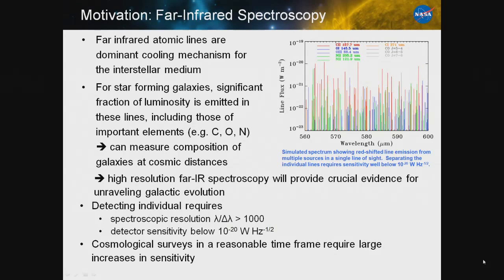And thus, high-resolution far infrared spectroscopy could provide us with crucial evidence to help us understand galactic evolution. However, this is not easy. It requires very high spectral resolution, and in particular, it requires extremely good detector sensitivity in order to resolve these lines without blending or confusion. So we're really trying to push the detectors to an NEP below 10 to the minus 20, and this would allow cosmological surveys in a reasonable time frame.